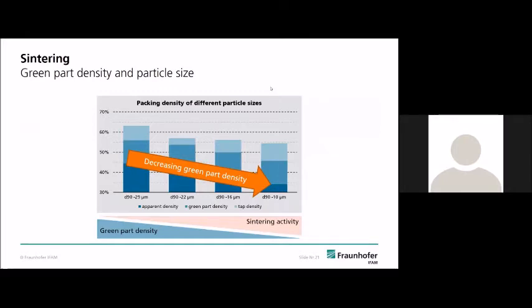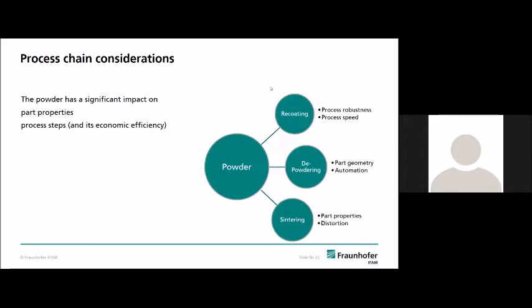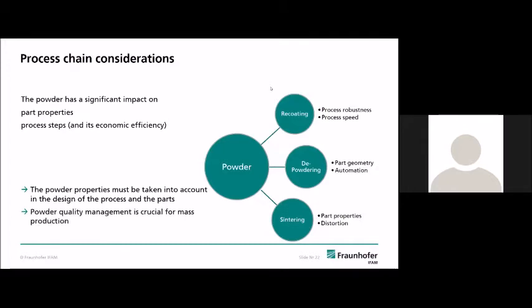We have done a lot of tests with powder mixtures and have found out that mixing powders, so standard powder plus additional fines, can be a good compromise between green part density, in this case, so stability of the green part, and sintering activity. I won't go into detail concerning this. So the powder has a big influence on the recoating process, on the depowdering and the sintering steps. This is also known from the beam-based processes that the powder has a big influence, but this has to be taken into account to set up the process and to design the parts in the end. The powder quality management is crucial for mass production, if you think of that.